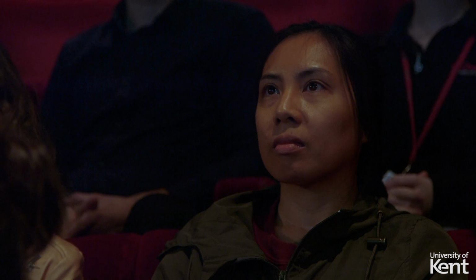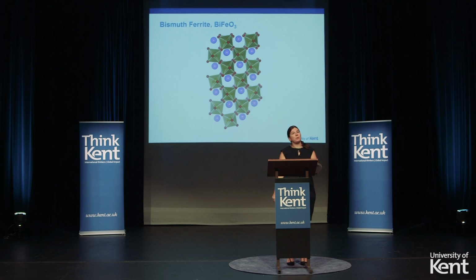However, there are many barriers to commercialization of bismuth ferrite. Firstly, it's difficult to make single phase. It has a complicated magnetic structure, which is not exactly ideal, and it has poor electric properties in that it has high conductivities and high leakage currents, which make it not useful as a commercial material. Our research centres on trying to improve the properties of bismuth ferrite by using the toolboxes that I've highlighted today in my talk, by replacing different ions to try and improve both the properties.